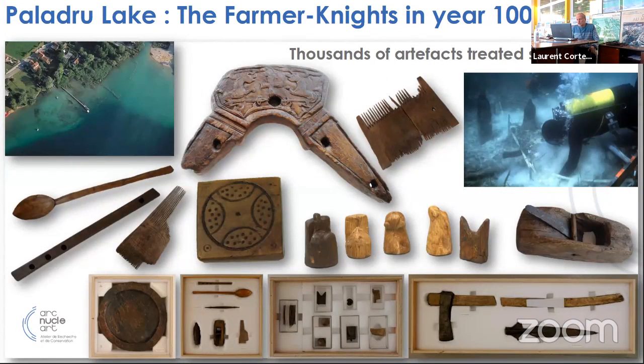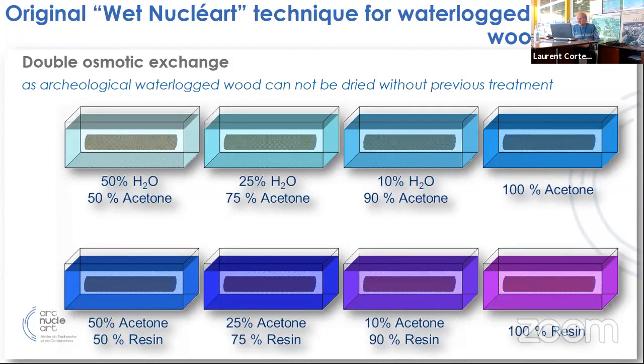But in the early 70s, we developed a method with radio-curable resin for the treatment of a very important collection of medieval wooden artifacts that were found in a lake near Grenoble. We were asked by the archaeologists to find a solution for this collection, and the problem was the impregnation step, as we cannot do like dry artifacts, because the artifact is full of water, and we cannot dry it.